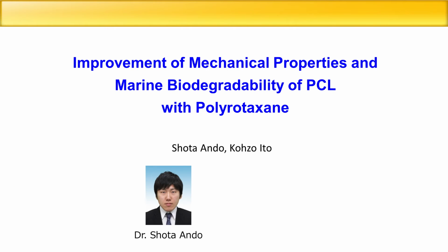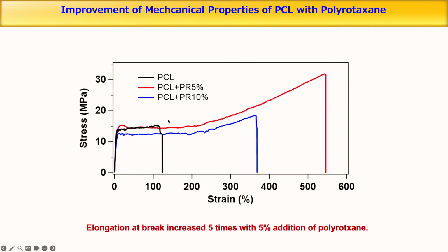So let me share some technology we're trying to develop in our lab. This is PCL, which is ocean degradable. Shown by this black line, the horizontal line represents the strain, and the vertical shows stress. You can see the elongation stress isn't that high. It'll break at about 100%. But if you include 5% of this necklace structure, it becomes much stronger. Even if you increase the strain by about 5 times, it won't break.